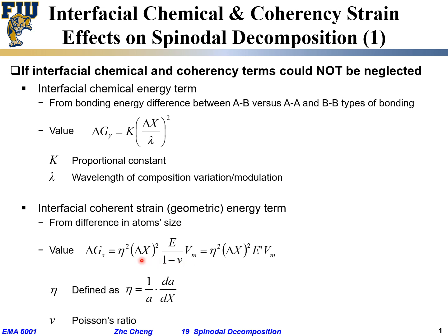The larger the composition fluctuation, the larger this geometric coherency strain energy effect. Similarly, the larger the lattice parameter change with respect to composition, the larger this coherency strain energy term. So these are the two additional contributions that in realistic and practical situations we quite often have to consider: one is the chemical interfacial term, and one is the coherency or geometric strain term.